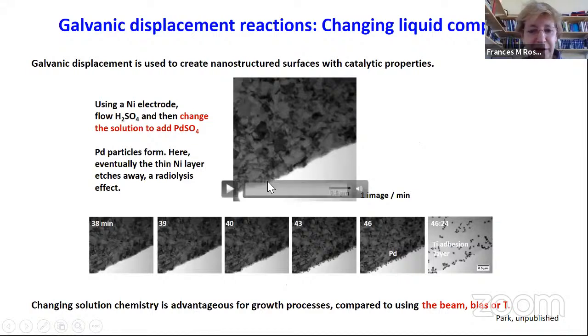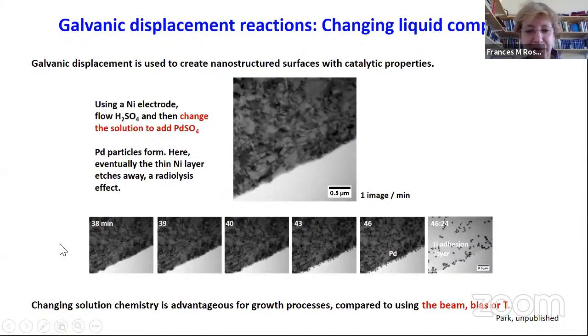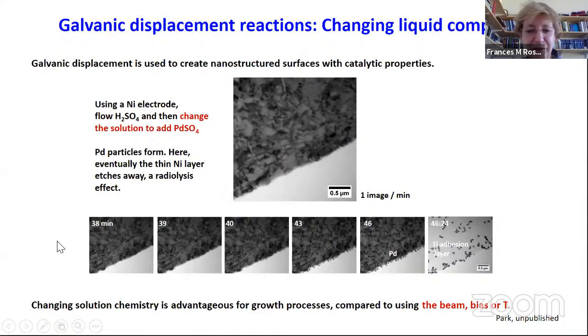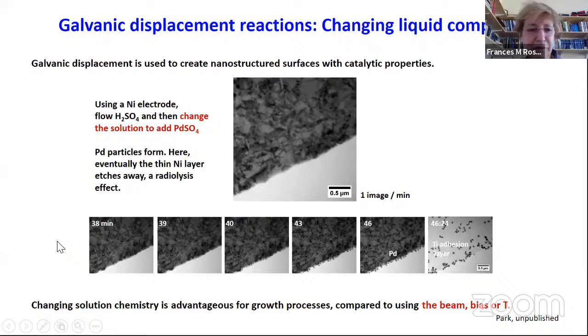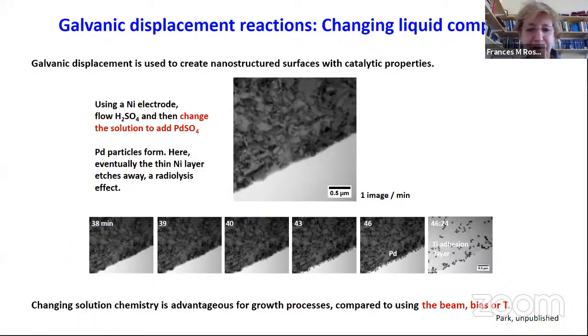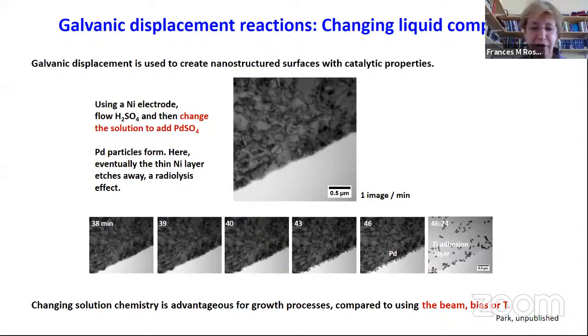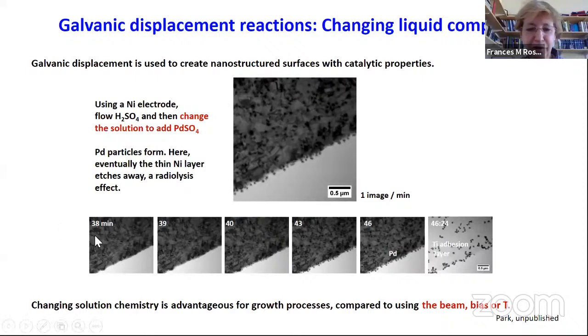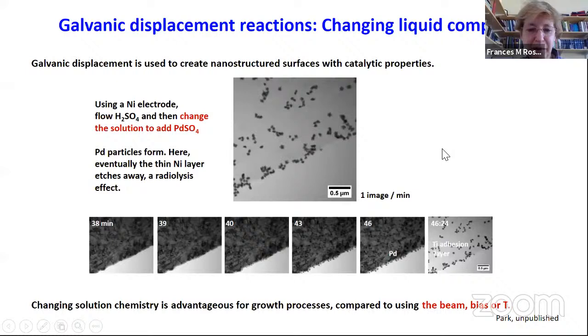Okay, and finally, galvanic displacement. This is an experiment where we don't apply a voltage, but we're flowing palladium ions over a nickel electrode, and you can see the formation of solid palladium and the dissolution of the nickel. It's not all electrochemical, there's electron beam effects here, but the principle is in there.